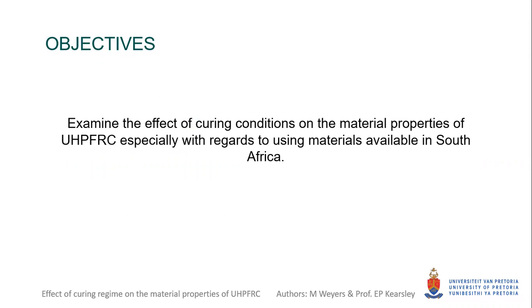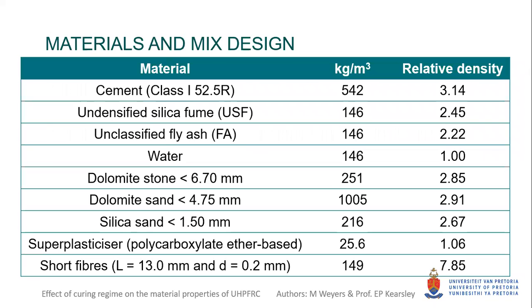Consequently, the focus of this study was to examine the effect of curing conditions on the material properties of ultra-high performance fibre reinforced concrete when using two different curing regimes, namely 25 degrees Celsius and 80 degrees Celsius water curing, especially with regards to using materials available in South Africa.